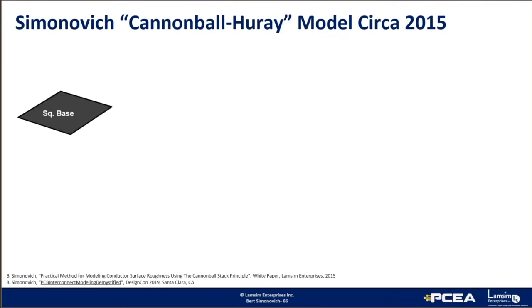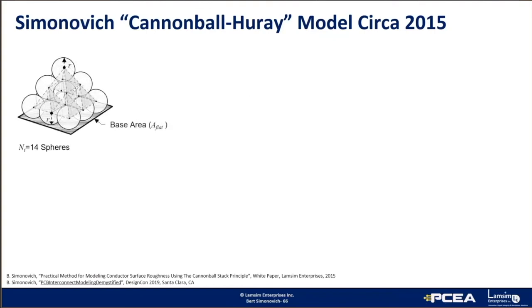We start with a square tile base. Then we stack 9 spheres on top of the first row, 4 spheres in the middle row, and 1 sphere on top. Now, if we can magically peer into the stack and visualize a pyramid lattice structure connecting to all the centers of the spheres, then the total height of the cannonball stack is equal to the height of 2 pyramids plus the diameter of a sphere.